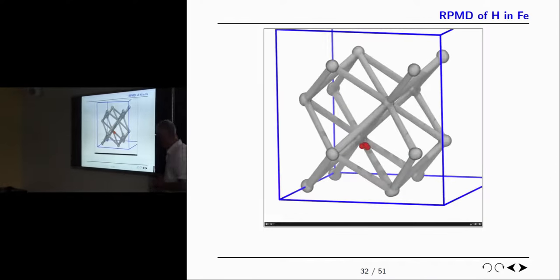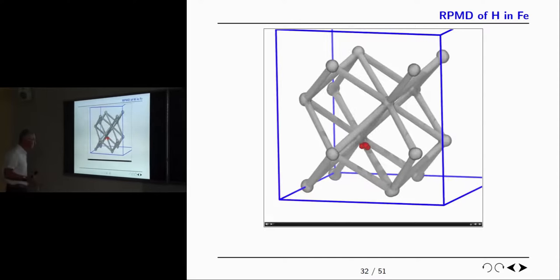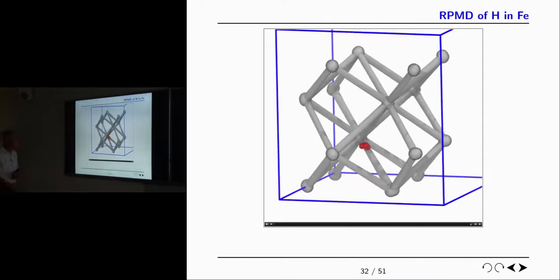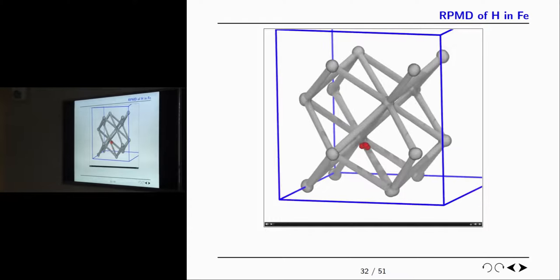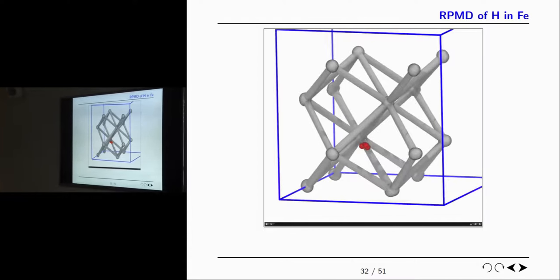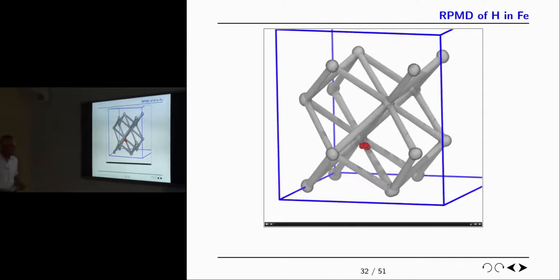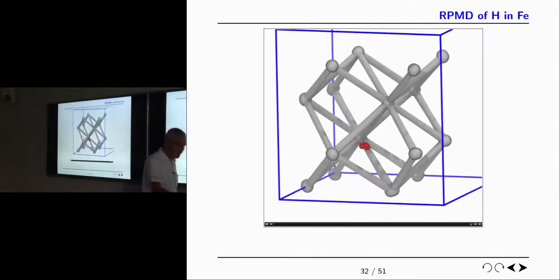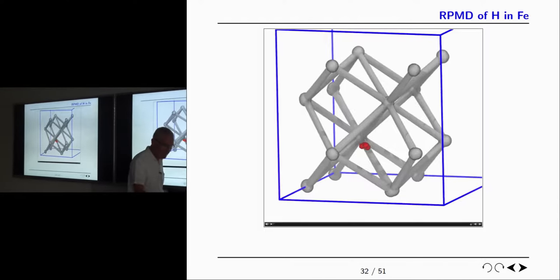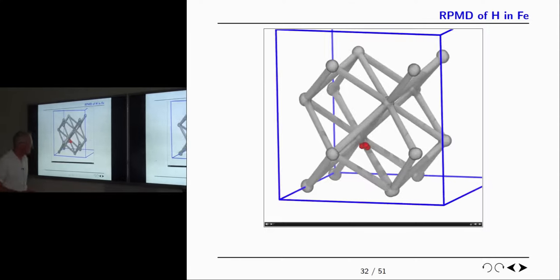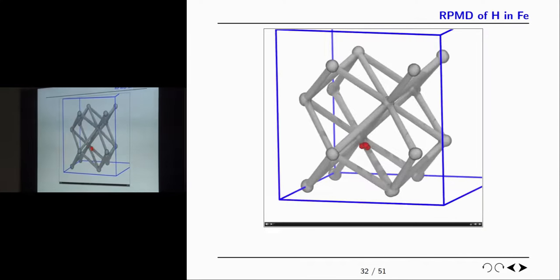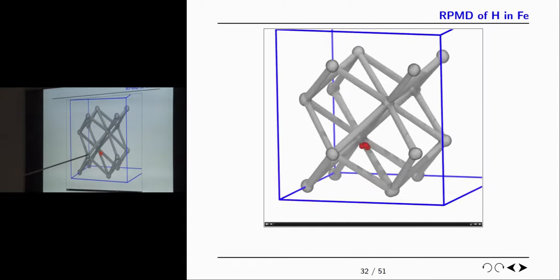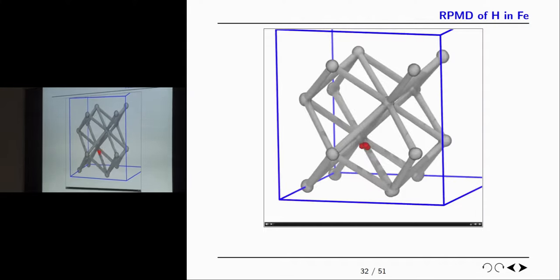And this is now, these are the little ring polymer beads vibrating in an iron lattice. So this is a fully quantum mechanical calculation. Not only are the electrons quantum mechanical through the tight binding parameterization, but also the ions are quantum mechanical through the Feynman path integral formalism. So each atom is actually a little necklace. There's only one hydrogen atom, there's only one proton, but here it's being represented as a set of replicas to represent its partition function.